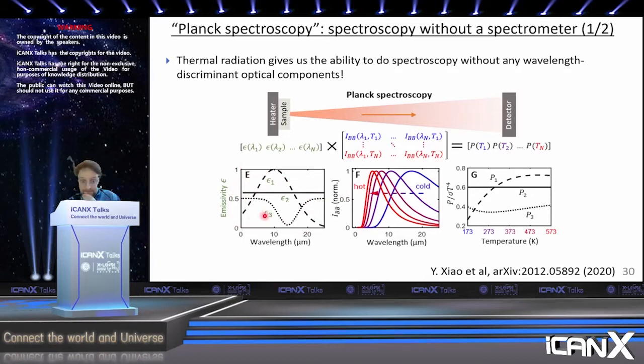It could be any sort of function that's bounded by 0 and 1 as a function of wavelength. The actual spectrum of thermal radiation given off when the sample is at some temperature is not only this emissivity, but this emissivity multiplied by the Planck distribution, Planck's law of thermal radiation. Here I'm normalizing Planck's law, all of them, to 1. In reality, of course, the hotter the object is, the bigger the spectral radiance is going to be. So you take this emissivity and multiply it by the Planck distribution. Of course, you integrate the whole thing because your detector is not measuring a spectrum, it's just measuring the integrated power.